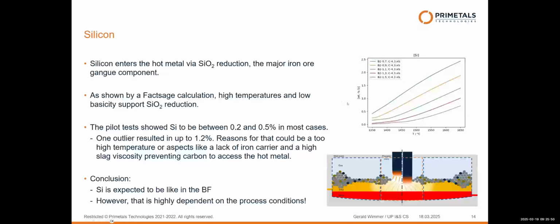Silicon, next topic. So silicon is coming, of course, from the gangue. There's a lot of silicon oxide in the gangue, and this can be reduced. How much of the silicon is reduced is, of course, depending on the reduction power. And there, of course, if we have this arcing, in the arc zone, we have enough temperature and carbon available to reduce silicon. But there is always a competition between the FeO and the SiO2. So always first, the iron oxide is reduced, and secondly, the silicon oxide.